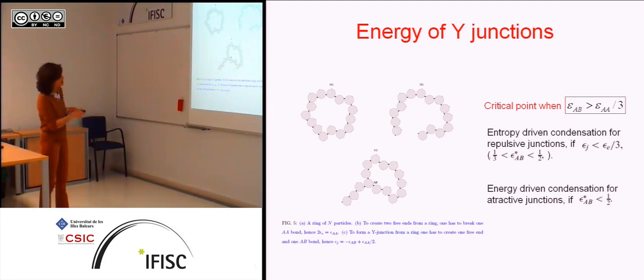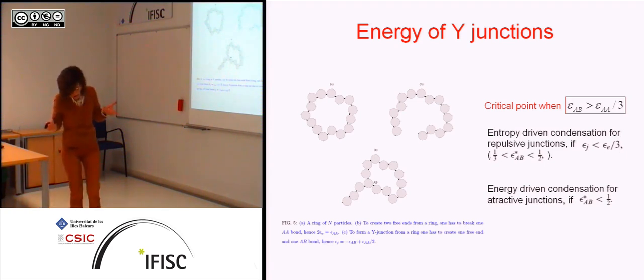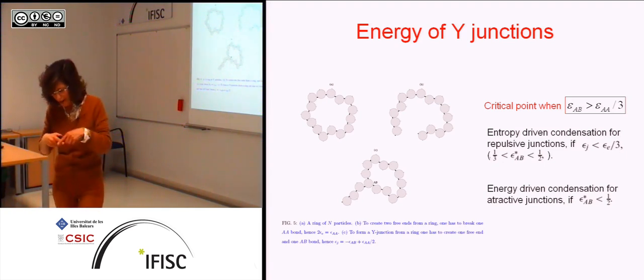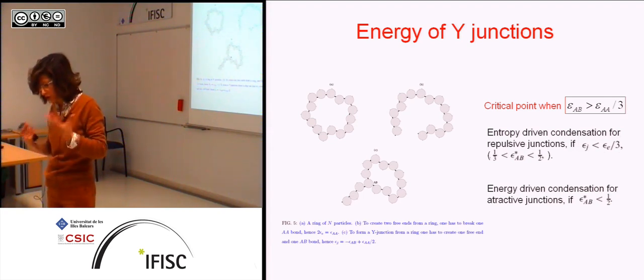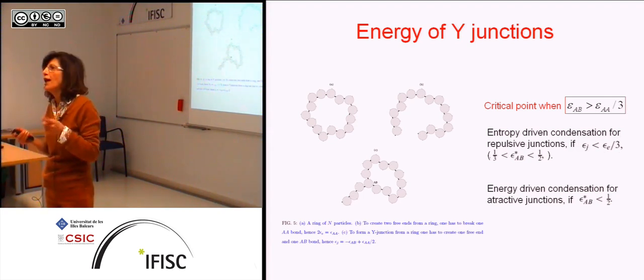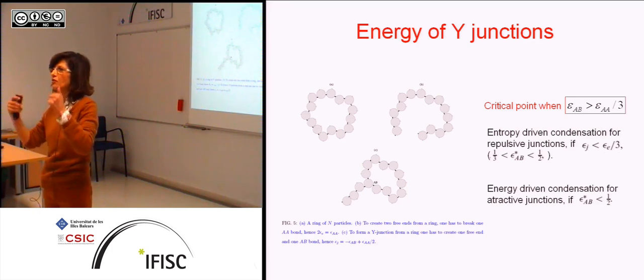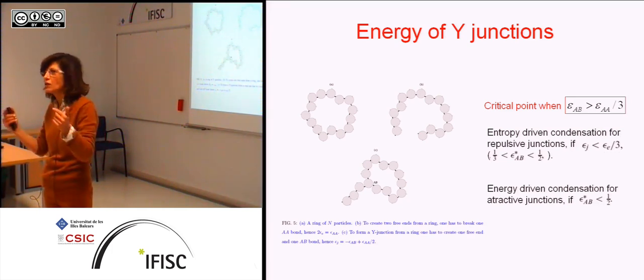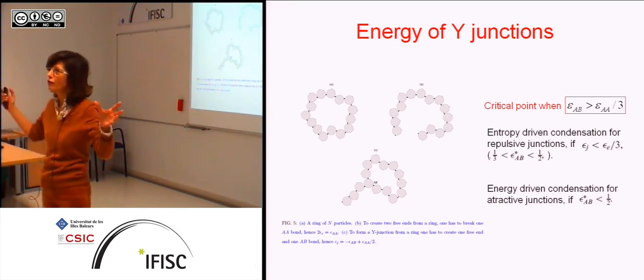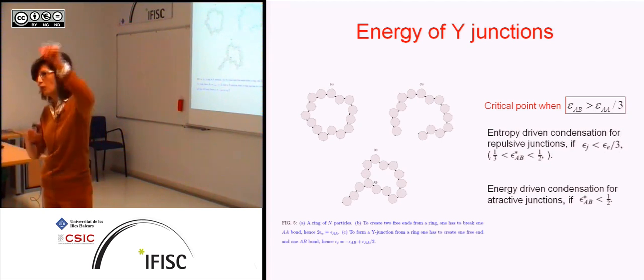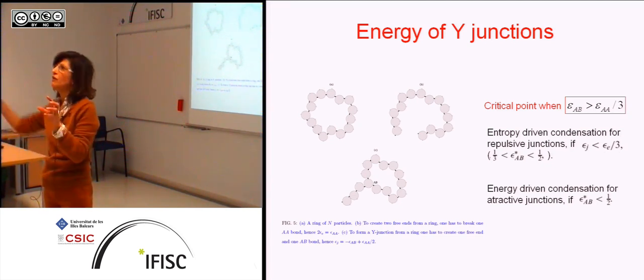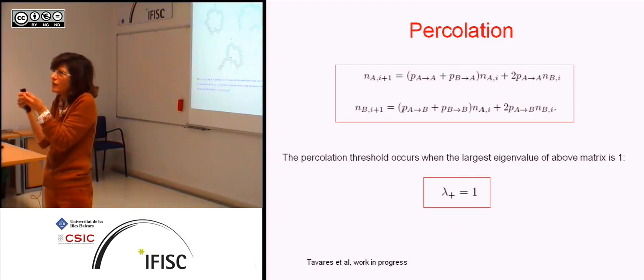But we can also see that there are energy-driven junctions because we can make this EAB more attractive. So now the final question is, we find that at the critical point we know the structure of the fluid, and what we would like to know is below the critical point, when the transition becomes first order, what does coexist? Do we have two network fluids? Do we have one network? Network means an infinite cluster. With a dilute fluid with finite clusters, or what?